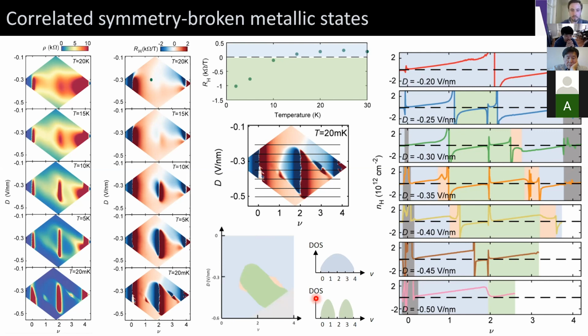And so the blue regions correspond to regions outside the halo, where the parent band is evidently intact and fourfold degenerate. And then this halo is a footprint of how far we can detune in filling factor and displacement field from the optimal conditions and still realize some symmetry breaking of these bands. So basically these bands gap and the degeneracy is reduced by 2. And then not shown, when we go to 1/4 and 3/4 filling, we get yet another symmetry breaking of this twofold symmetric band. And now this orange region has no remaining degeneracies.